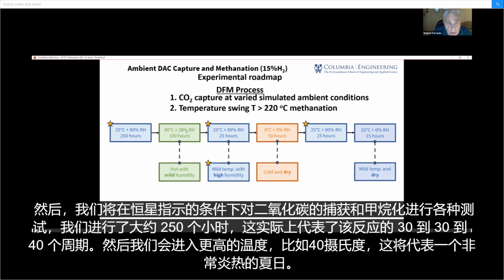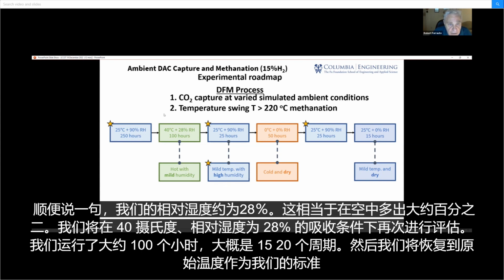And then we would go to a higher temperature, such as 40 degrees centigrade, which would be representative of a very hot summer day. We have a relative humidity of about 28%. By the way, this corresponds to about 2 mole% in the air. And we would evaluate again at the conditions of absorbing at 40 degrees centigrade with 28% relative humidity. We operated for roughly 100 hours, which may have been maybe 15, 20 cycles.